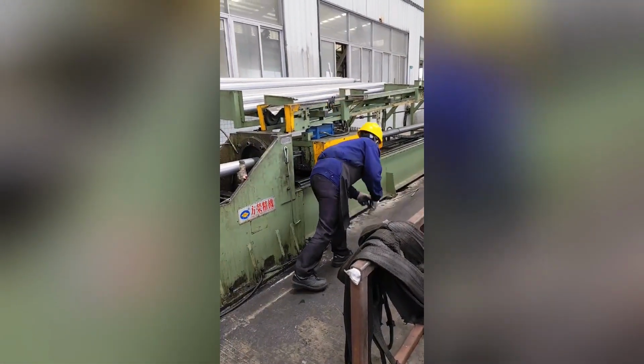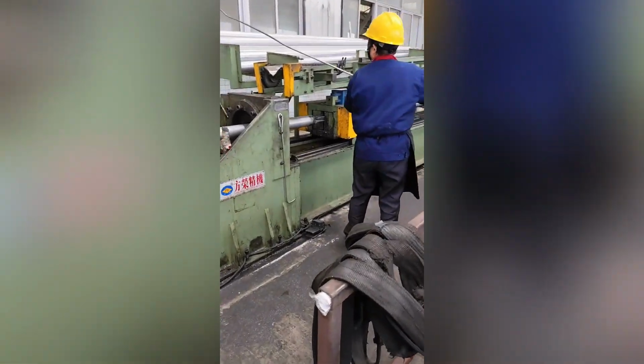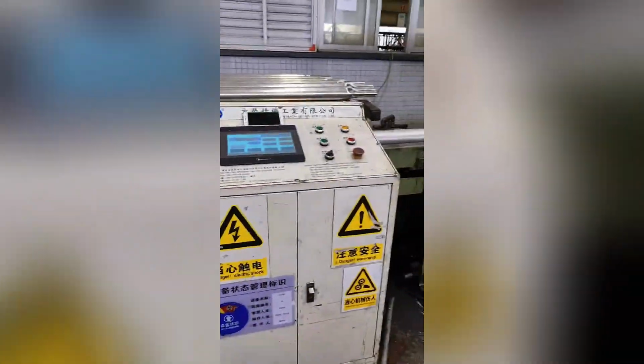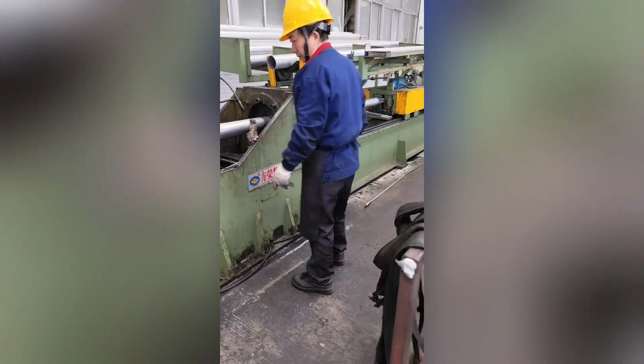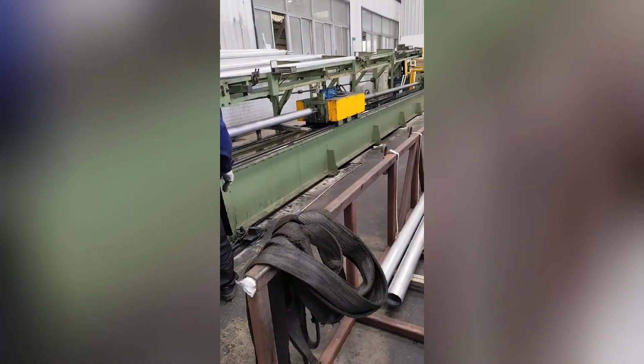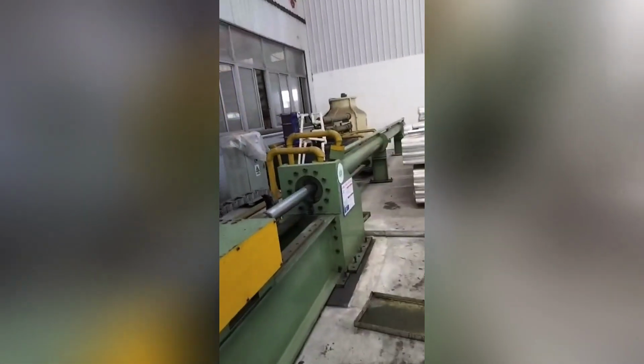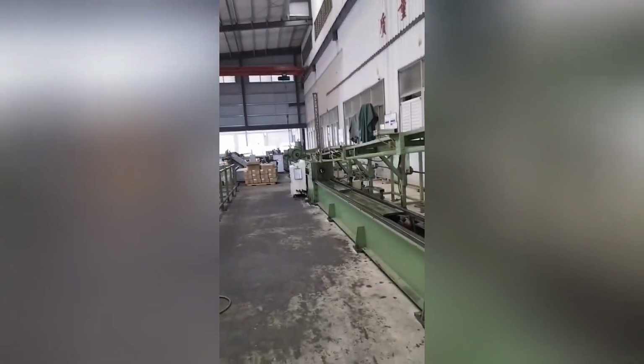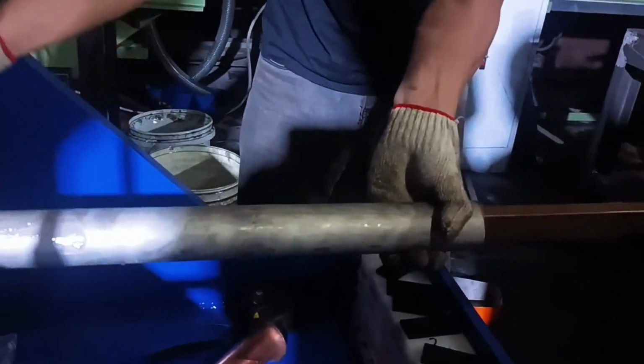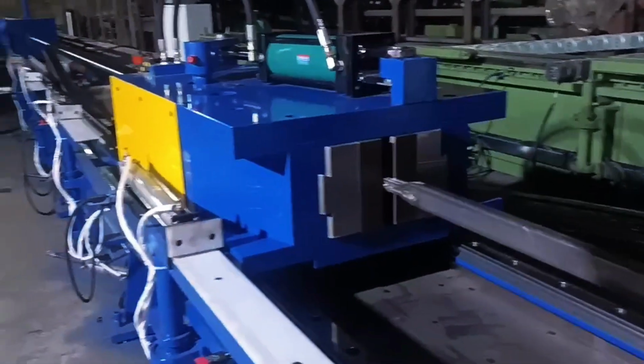Then we have the drawing carriage, a moving slab that grabs the front end of the tube or bar. The die box holds the carbide or diamond die. The tube is pointed or swaged at the end to fit through the die. A gripping jaw on the carriage locks onto that pointed end. When the hydraulic cylinder retracts, it pulls the carriage and thus the tube through the stationary die. The control system allows variable pulling speed and force monitoring. Safety features include light curtains, emergency stop, and hydraulic overload protection.